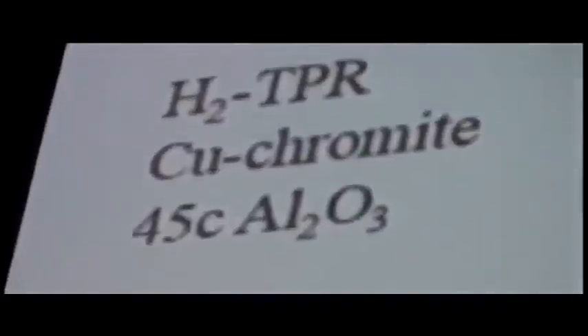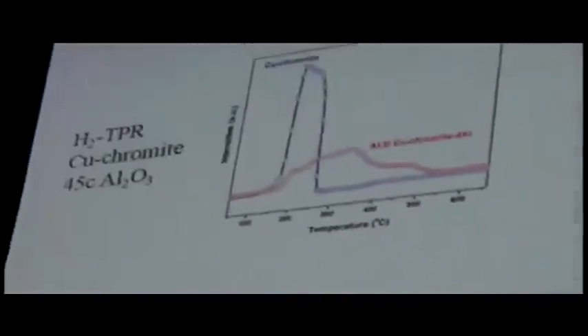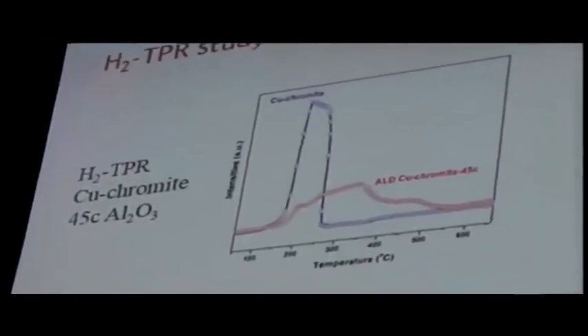One of our standard tools for studying catalysts, of course, is temperature programmed reduction. There have been many talks that have used that in the past. If we look at the TPR of the copper chromite catalyst shown in blue here and the aluminum ALD overcoated copper chromite catalyst shown in red, the first thing you can see is that there's a dramatic change in the temperature programmed reduction of the copper material here. And I emphasize the copper material that we're talking about. In actuality, in this type of TPR experiment, all you know is that there's a change in the composition of the gases that are coming off here. And I'll show why that's important in just a second.